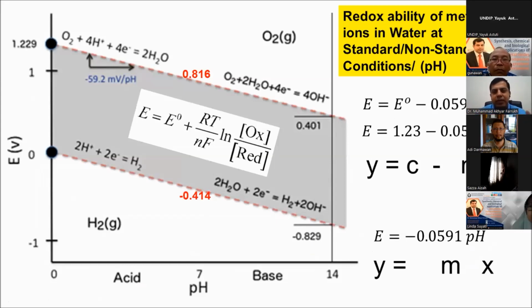This is the electrochemistry. That means the plant extract or the microbes are acting as the reducing agents. So if you use a simple plant extract, then it might be difficult to reduce the graphene oxide or the metals into nanoparticles. And the reason is because this graph is showing that with the change in pH, there is change in the potential of the half cells of the water. This one has the standard potential of 1.229, and for this half cell it is 0. The only thing important over here is that when you increase the pH, these reduction potentials are going to decrease, and these are at 7 pH, that means when the water is neutral, and these are at pH 14.